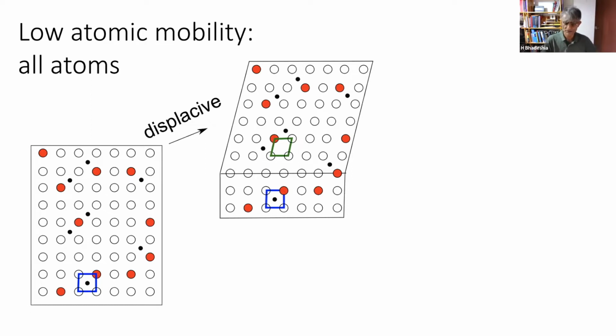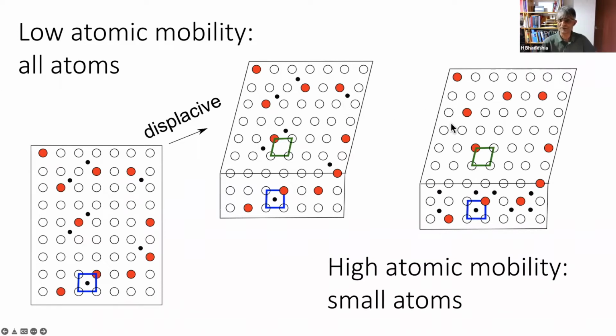And there is a second kind of displacive transformation in which the lattice of large atoms is displaced into position, just as over here, but the interstitial atoms are able to partition into places where they are most comfortable. So we have a composition change with respect to interstitial atoms, but all the crystallographic characteristics of a displacive transformation are maintained. And this is when, we are in a regime of temperature where small atoms are mobile, but large atoms are not. Now, obviously, these are not equilibrium transformations because even these red atoms might want to partition. So not only are the atoms not at equilibrium, but you have this large strain energy term. So these transformations will only happen in certain circumstances, which I'll outline later.